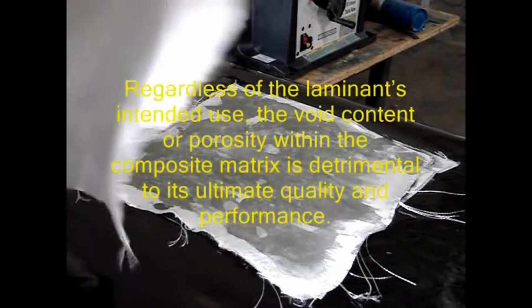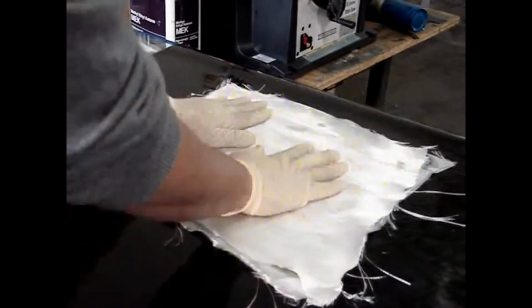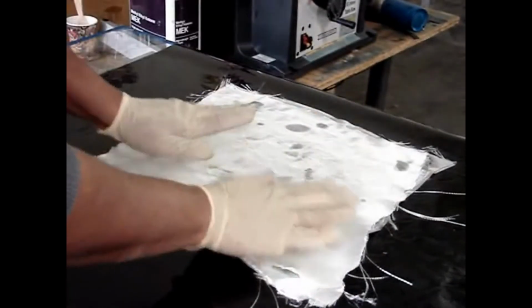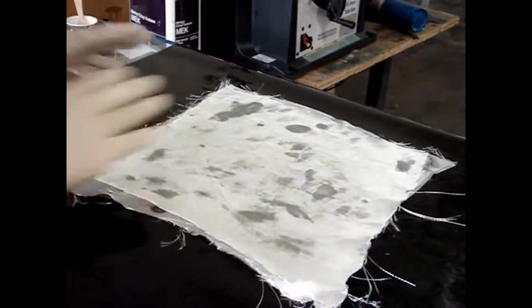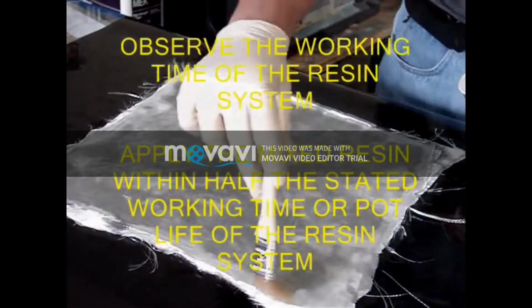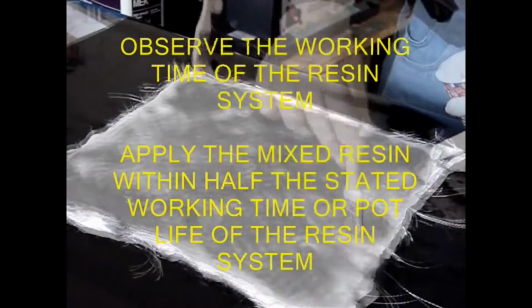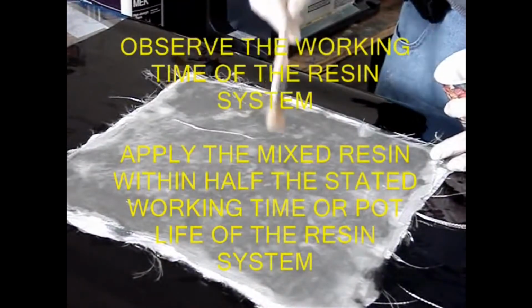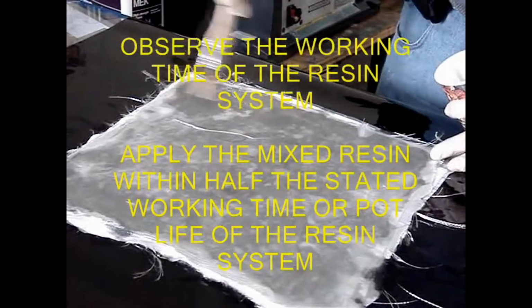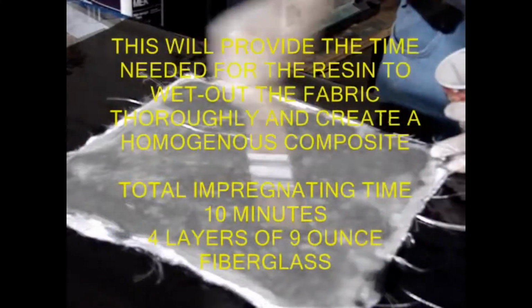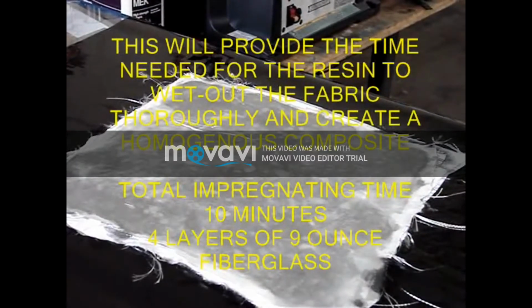Regardless of the laminate's intended use, the void content or porosity within the composite matrix is detrimental to its ultimate quality and performance. We must observe the working time of the resin system and apply the mixed resin within half of the stated working time or pot life of the resin system. This will provide the time needed for the resin to wet out the fabric thoroughly and create a homogeneous composite.